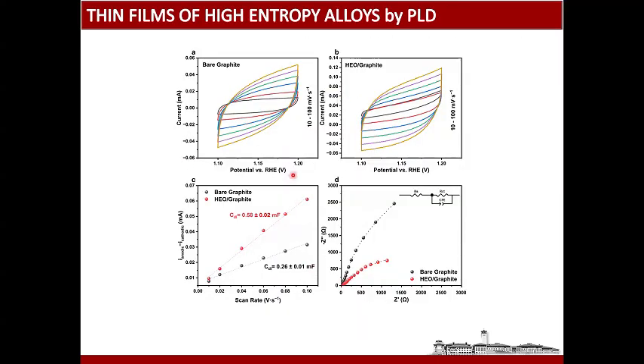We did electrochemical surface area analysis, so introducing high entropy alloy. Of course this will be an oxide form, because pulse laser deposition is in open air, and during the pulse laser deposition, the local temperature increases and that oxidizes the material. So we did this electrochemical surface area analysis.